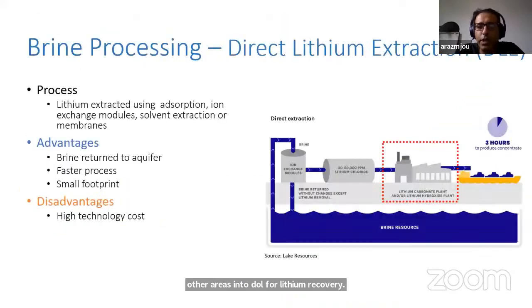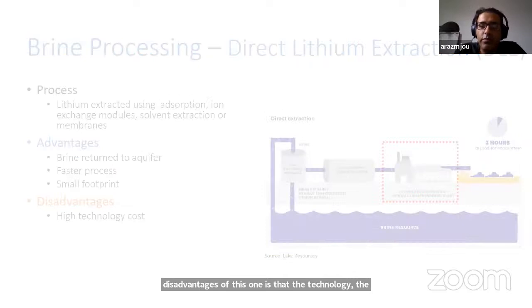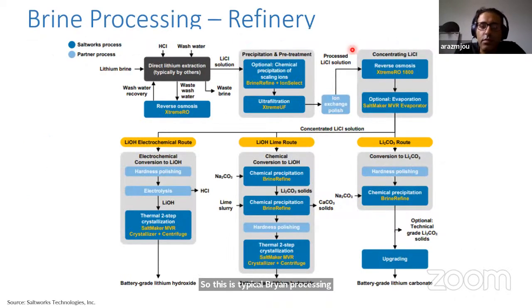So this is a typical DLE process. Lithium is extracted using adsorption, ion exchange, solvent extraction, and membranes. The main advantage is that brine returns can be retained in the aquifer. It's a fast processing and requires a very small footprint. And the main disadvantage is that the technology is expensive. So this is typical brine processing for DLE. It starts from the pre-treatment and then goes into different concentrated lithium chloride solution and finally producing battery-grade lithium hydroxide.